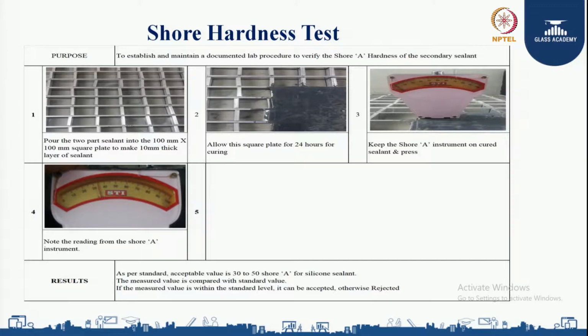This makes a 10 mm thick layer of sealant. Allow the square plate 24 hours of curing. Keep the shore A instrument on the cured sealant and press, then note the reading from the shore A instrument.